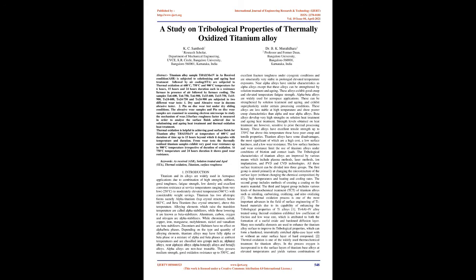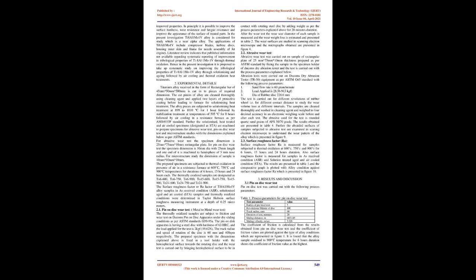Depending on the type and quantity of alloying elements, titanium alloys may have fully alpha or beta phase or a mixture of alpha and beta phases at ambient temperatures and are classified into groups such as alpha alloys, near-alpha alloys, alpha-beta alloys, and beta alloys. Alpha alloys are non-heat treatable. They possess medium strength, good oxidation resistance up to 550 degrees Celsius, and excellent fracture toughness under cryogenic conditions, and are structurally very stable in prolonged elevated temperature exposures.